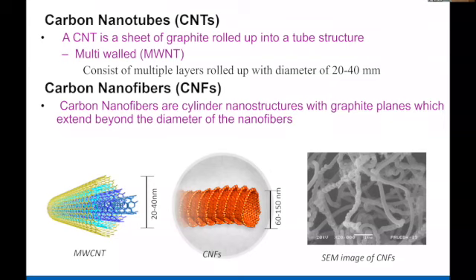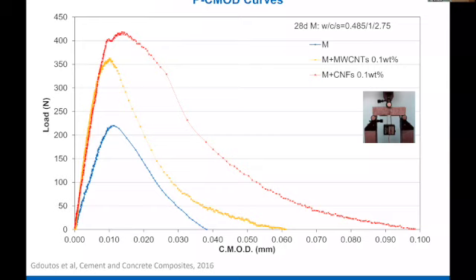And I'm going to show you some slides of performance of cement-based composite reinforced with carbon nanofiber or carbon nanotube when they're well dispersed. And when they're well dispersed, we use a very, very small amount. For example, here are the results of 0.1%. And you can see these are the classic fracture tests, load versus crack mouth opening displacement. And you can see the blue curve is unreinforced and the top is with carbon nanofibers. And we have essentially doubled the flexural strength and also maintained an excellent strain softening response.